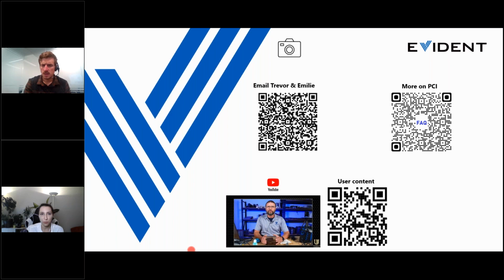So it is a good application for PCI with thin materials. Somebody also mentioned weld overlay. Again, changing from one material to another can be very obvious. We can see the weld, but we should be able to penetrate and to look on the far side. So depending on the material, of course, if sound can't go through, well, then it just can't go through. But in theory, yes, that could work very, very well on weld overlays.